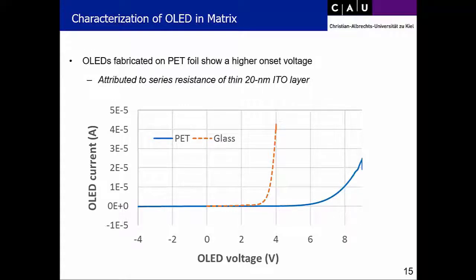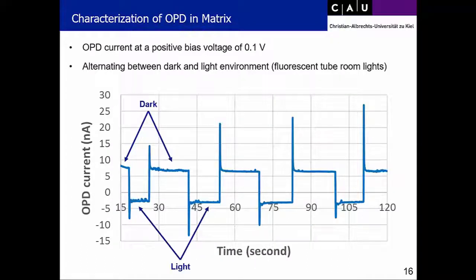For comparison, we also plot the current voltage characteristic for glass, and you can see that the onset voltage is quite a bit higher, and we think that, or we know that this is due to the fact that we have only 20 nanometers of ITO, while on the glass substrates we have 120 nanometers of ITO, so the serial resistance is a lot higher here for the PET foil than it is for the glass substrate. So that is definitely something that needs to be improved, to use either thicker ITO or to add additional metal for conductivity. And then we characterize the OPDs as well.